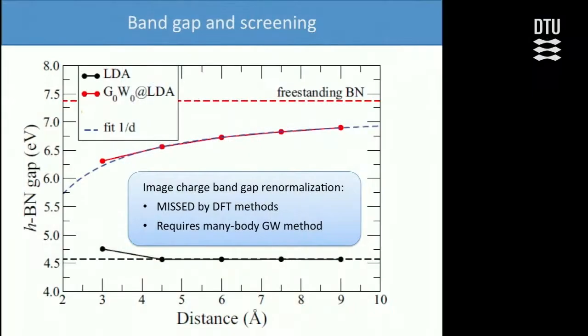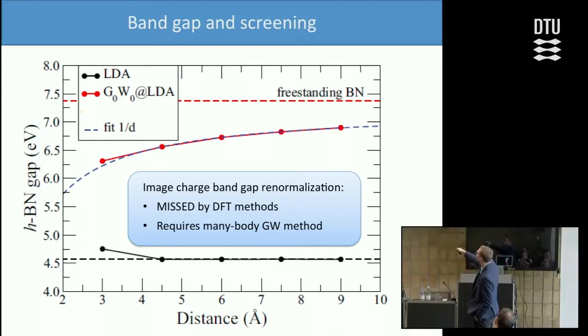This is a 1-over-distance fit to the GW calculations of the band gap in hexagonal boron nitride. You can see this is the gap in freestanding HBN. So we can actually reduce the gap quite significantly by putting it onto a layer of graphene.